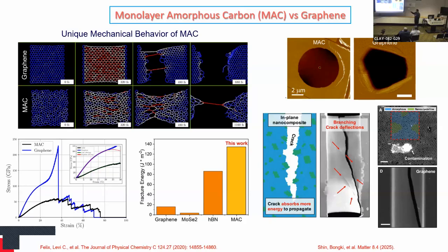Recently there was an experimental paper on that as well. They show that it has a very high fracture toughness, which is very unique among 2D materials. Compared with graphene, MAC has a very high fracture toughness. That is because of its random structure. Once a crack propagates through the material, it changes direction because of these small crystallites sitting there. It creates crack deflections that absorb energy, so your fracture toughness increases.